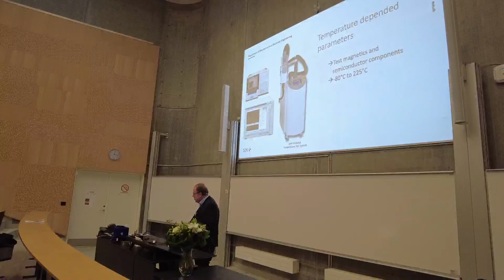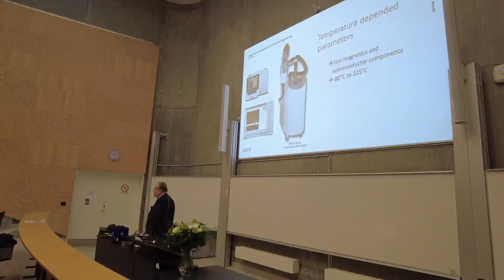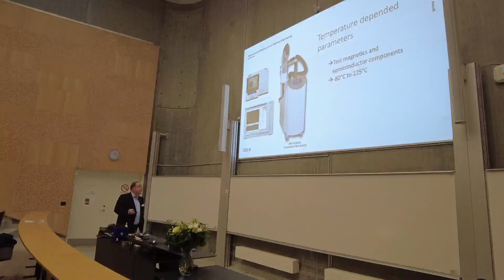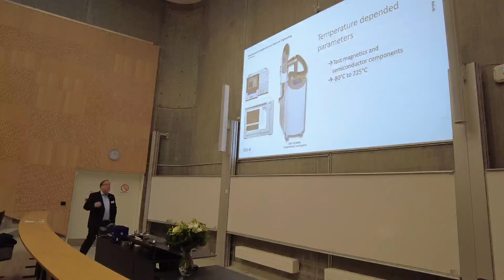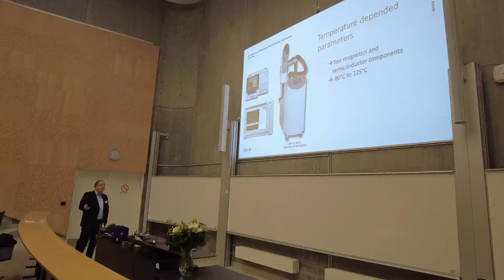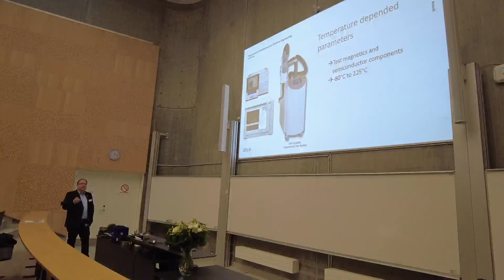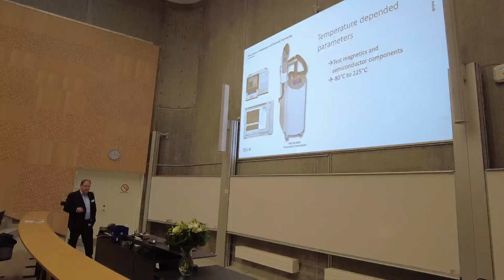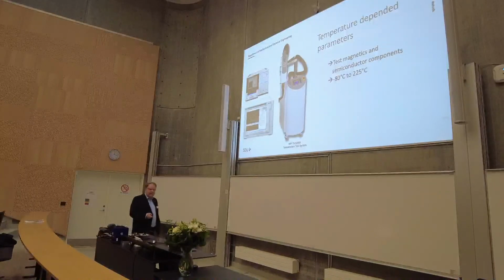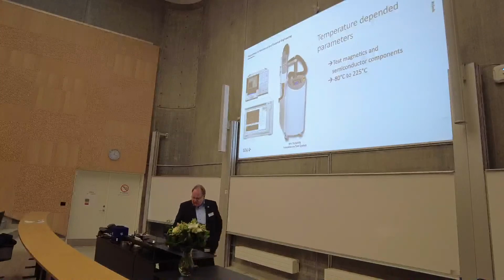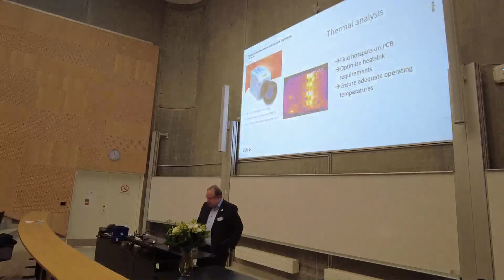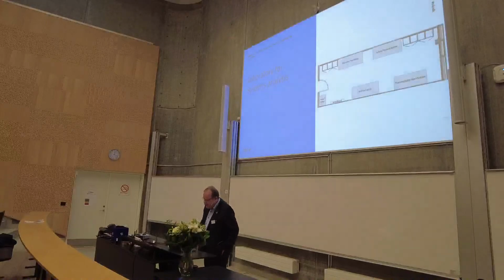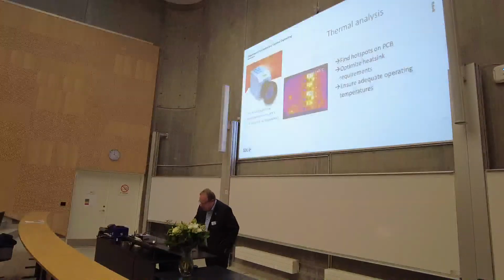To expose them to low and high temperatures, we also have a thermo stream there, which is also available in Sonderborg. We have two setups, one in Sonderborg and one in Odense, but this Sonderborg setup does not belong to X-Power, so I present this setup here. Here we can expose the switching devices to temperatures from -80 to 225 degrees Celsius and investigate their switching behavior under these conditions. Yes, and then the second lab about thermal analysis.